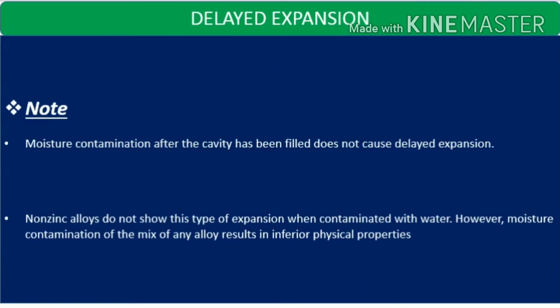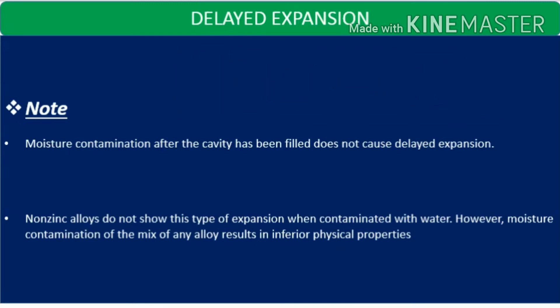Moisture contamination after the cavity has been filled does not cause delayed expansion — only during manipulation of the amalgam. Non-zinc alloys do not show this type of expansion when contaminated with water. However, moisture contamination of the mix of any alloy results in inferior physical properties. Therefore, stringent protocols must be followed: proper rubber dam application, proper isolation of the operating field, proper cotton rolls in place, and no moisture contamination.